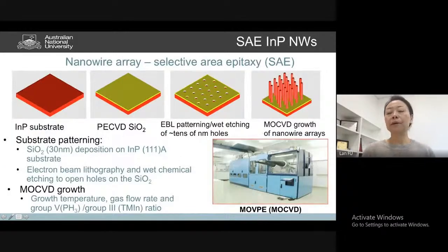So now I'm going to talk a bit more focused on indium phosphide nanowires, which is the material we do a lot of research on in our lab. As I said, we normally grow them using an epitaxial growth technique, the selective area epitaxy, where we use a thin layer of dielectric as a template to create a nanowire array with well-designed diameter and spacing. And then we put it into this MOCVD reactor. We pass in the group 3 and the group 5 precursors. For indium phosphide it will be trimethyl indium, and for the phosphide we use phosphine gas.